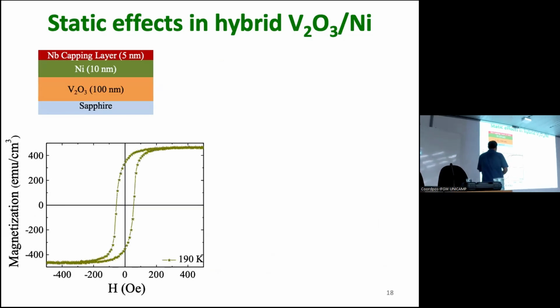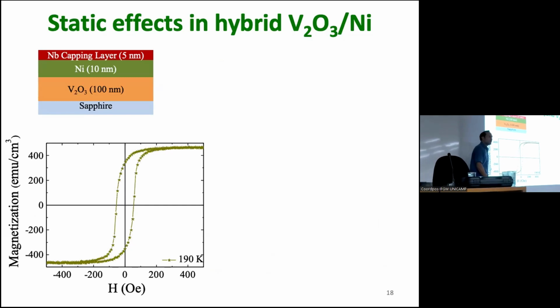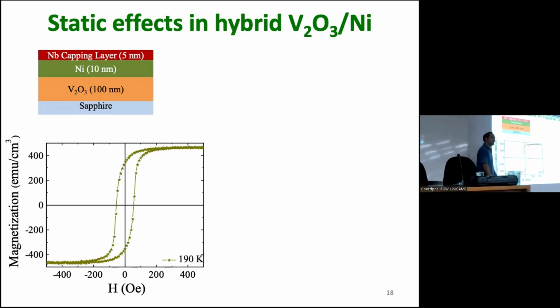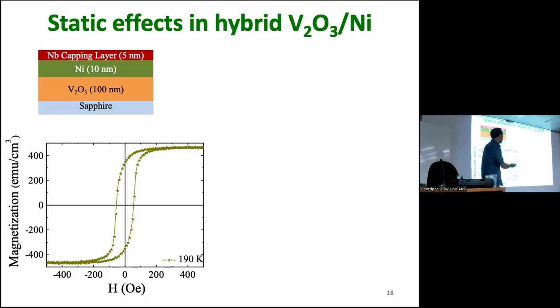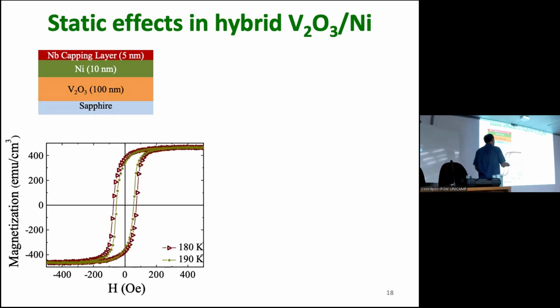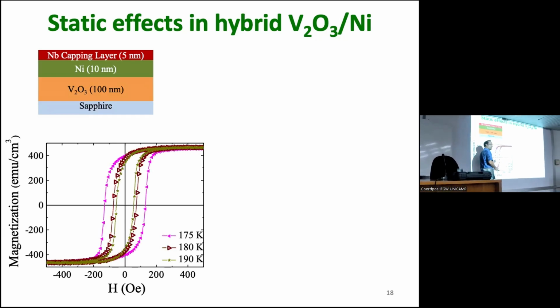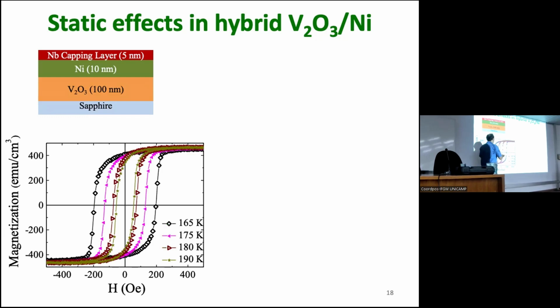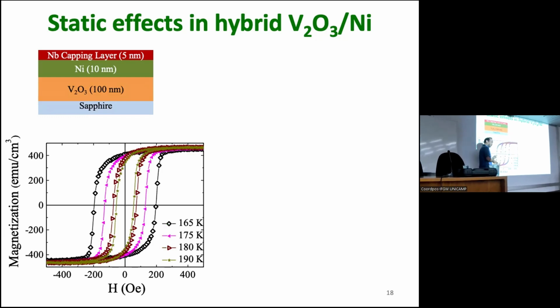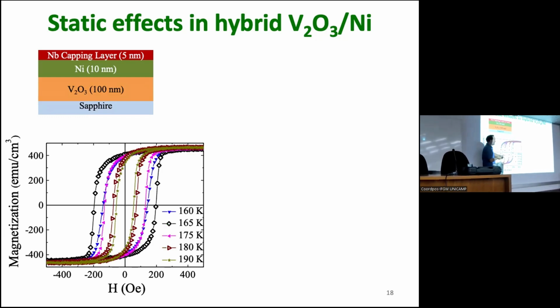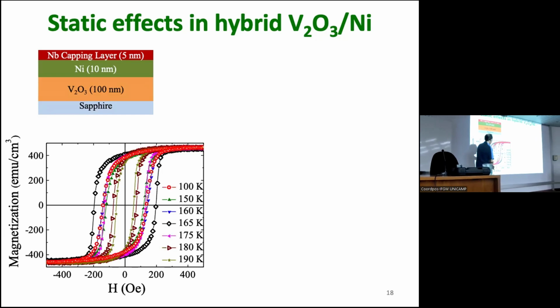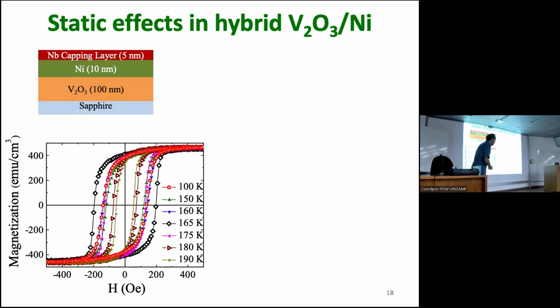So here is the standard thing that you can do. You go to your VSM, and then you measure magnetization as a function of the field, and then you see how the hysteresis curve looks for your material. And then you increase the temperature to go through the transition of vanadium oxide, and then you see that this is kind of increasing, which kind of makes sense. And then at some point it's huge, and then it goes back, and then goes back again, and then it stays there. So the coercivity is going up, and then it's going down.